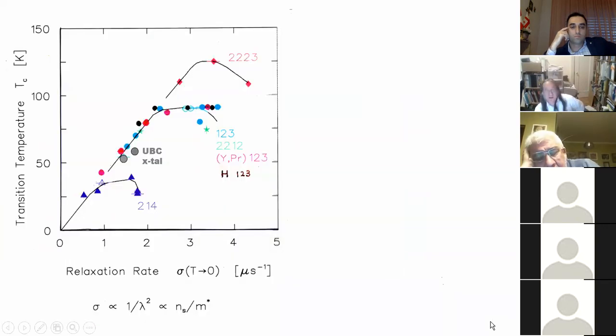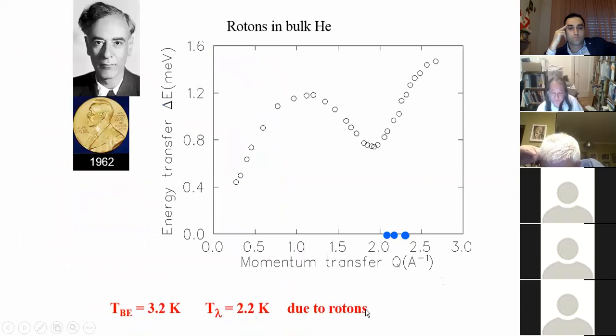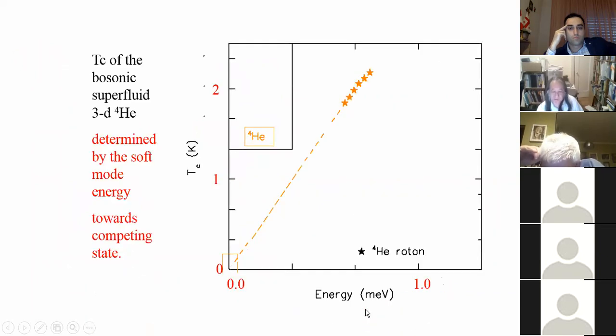Okay, so the way to show you that this competition with the magnetic phase is important is to remember that for a given superfluid density, for example, this 2-1-4 system is showing lower TC than the 1-2-3 system. And the difference is that it is known that this 2-1-4 system is closer to magnetic order. And actually, let me skip this thing.